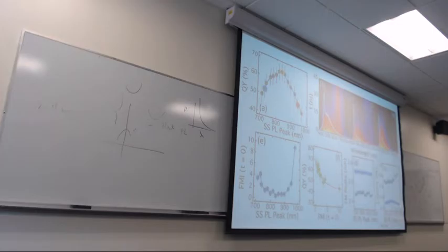The question is, when you go to your quantum dot, your K vector should depend on the size of the primitive unit cell. If your primitive unit cell is at least 10 times smaller than the size of the system, then your K approach would be fine. But if it is comparable, twice larger, or 3 times larger, then of course we cannot really talk about band structure. It behaves more like a cluster, more like a molecule. But for your 4 nanometer or even probably 2 nanometer quantum dots, you're probably safe to use your favorite bulk picture of band structure.